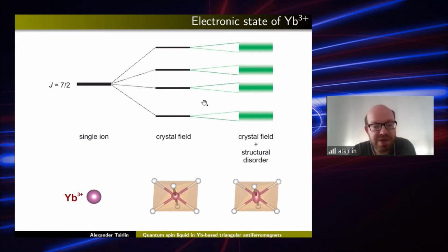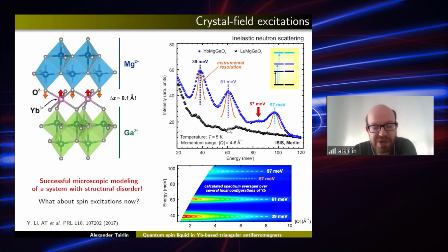And that's exactly what we saw in this material when we went to look at the crystal field levels with inelastic neutron scattering. So here you see the experimental pattern, and you see that all 3 peaks are much broader than the instrumental resolution, and there is even some additional shoulder which should not appear in the normal ytterbium case. Eventually, we were able to reproduce this picture quite well. I won't go into details, but I will only try to give you the general idea why this disorder effect takes place and where it comes from.